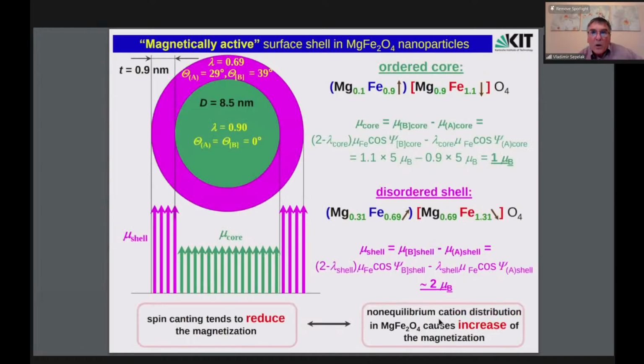And if we know information from Mössbauer spectroscopy about the ionic configurations and the degree of inversion, and about spin configuration, about the degree of inclination or deviation, spin canting angles, we can calculate on the basis of Néel theory of ferrimagnetism, the magnetic moment for the core, simple